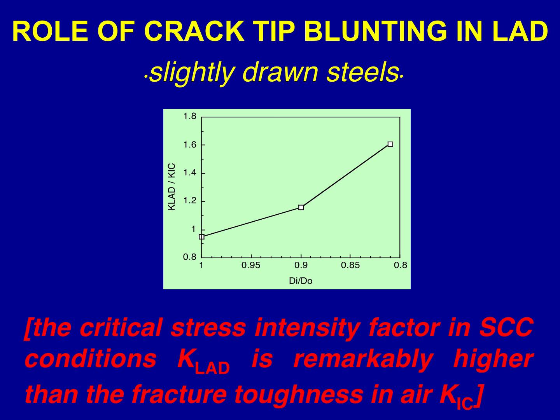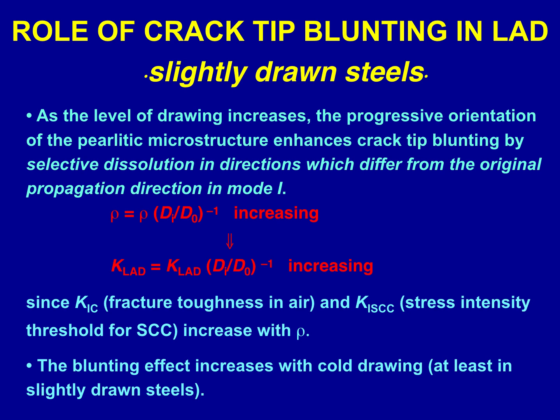Role of crack tip blunting in localized anodic dissolution. In slightly drawn steels, the critical stress intensity factor in stress corrosion cracking conditions, K-LAD, is remarkably higher than the fracture toughness in air, K1C. With regard to this role of crack tip blunting, as the level of drawing increases, the progressive orientation of the pearlitic microstructure enhances crack tip blunting by selective dissolution in directions which differ from the original propagation direction in mode 1.